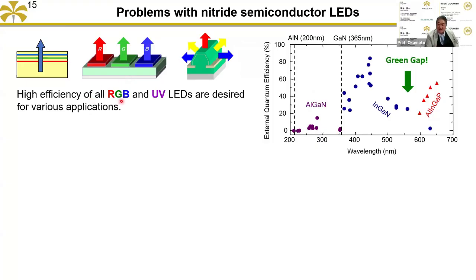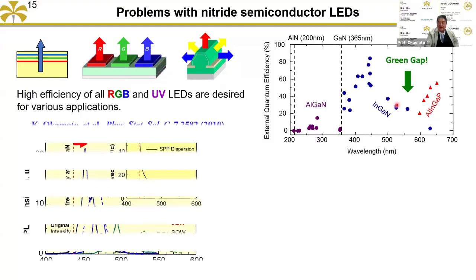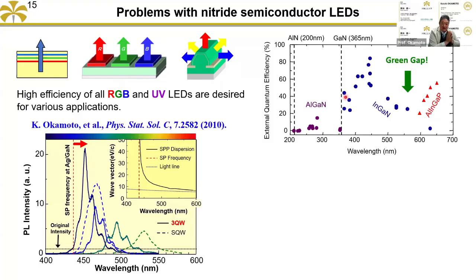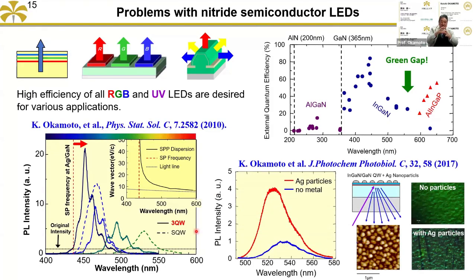Then we want to make an RGB light source for a no-loss white light LED, and also we want to use that for micro displays. In this case, high efficiency RGB emission is very important. Next, we want to try to enhance the green light emission. But silver is good for the blue light, and gold is good for the red light. If we change the sample to green light emission, with increasing emission wavelength, the enhancement factor becomes lower and lower. In the green light region, the enhancement factor is almost 2 or 3 times. We can control the resonance peak by changing the size of the particle, but we cannot control the coupling condition. That size is a good match to the green light, but still the enhancement factor is only 4 times. That's still difficult.